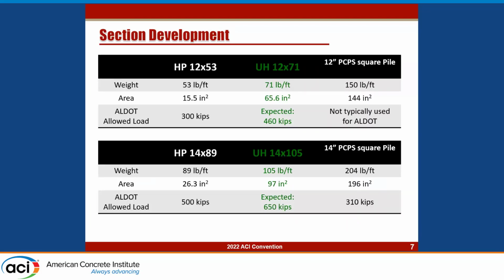Now, comparing our designed sections to their alternatives, we get an idea of where our piles fit. For both piles, we were able to stay within that 20 pound per foot goal that we set out. We also see a substantial increase in cross-sectional area, as well as expected load. For the UH 12x71, we get a 54% increase in load compared to the HP 12x53, and we get a 32% increase for the UH 14x105 compared to the HP 14x89.